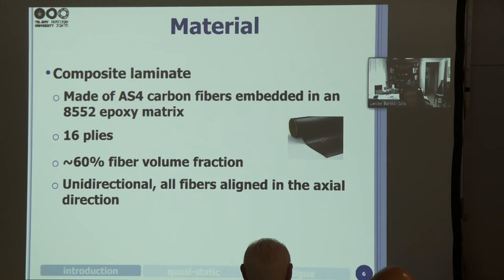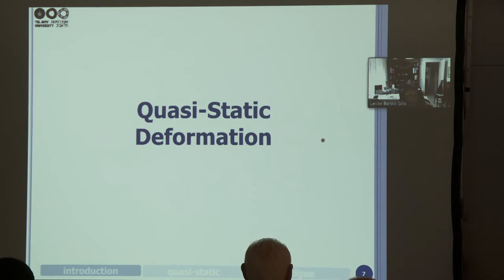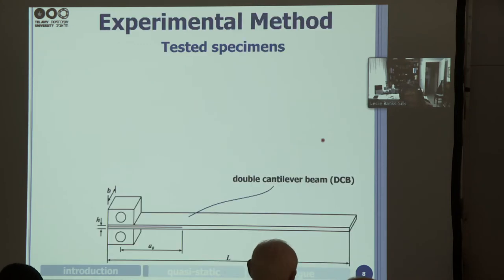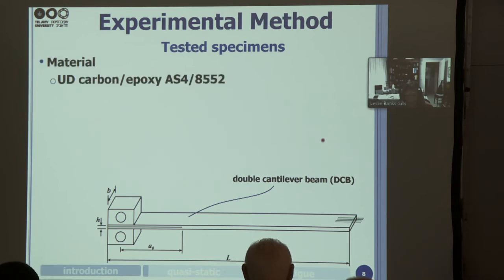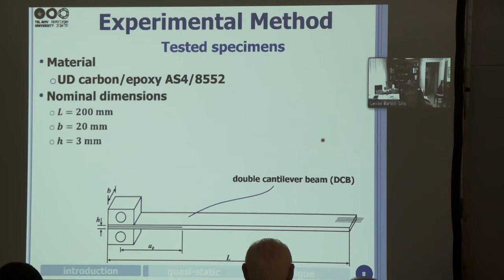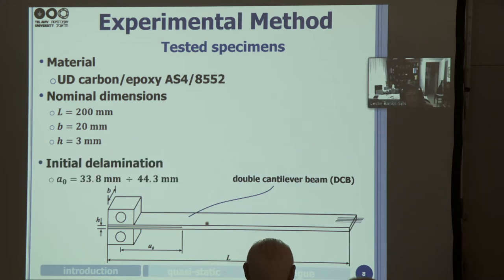The material is unidirectional, and all fibers are aligned in the axial direction. So let's look at quasi-static testing. Here's our DCB specimen. And as I said, it's made of a carbon epoxy AS4-8552. The nominal dimensions: the length is approximately 200 millimeters, the width is 20 millimeters, and the height of the specimen is 3 millimeters. And the initial delamination length was between 33.8 and 44.3.